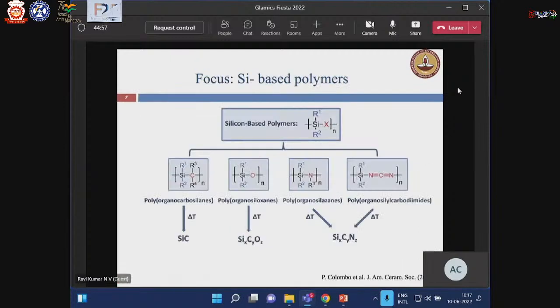Our group has been working on silicon-based polymers. We initially started to work mostly on non-oxide materials containing silicon, carbon and nitrogen. And in recent times, during the last 5-6 years, we have been working on silicon oxycarbide. What kind of ceramic composition it ultimately leads to depends on what goes into the backbone of the precursor. For example, if you use polyorganocarbosilane, you get silicon carbide eventually; if you start with siloxanes, you end up with silicon oxycarbide. And when you start with silazanes or organosilyl carbodiimides, you end up with silicon carbonitride.